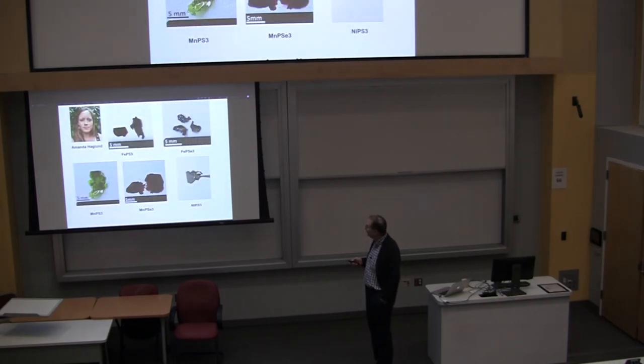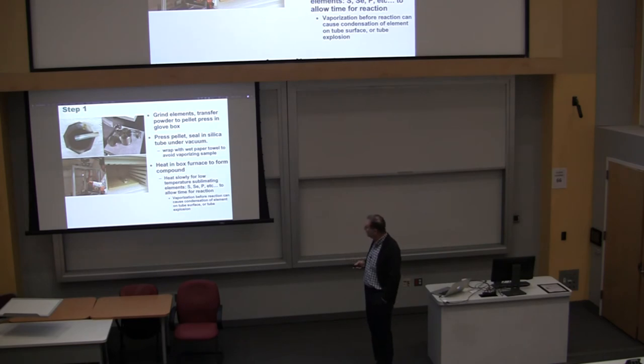So Amanda has grown lots. This is just a handful of the kind of things she grows. She's developed a whole bunch of tricks that she uses. She does a lot of work in the glove box and seals things under vacuum. When she seals the tubes, she's careful to keep the bottom end of the tube cold so it doesn't volatilize anything when you don't want it to. I think she wraps it with a wet paper towel.